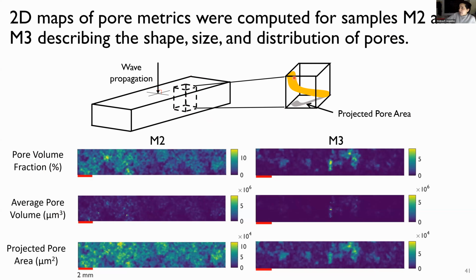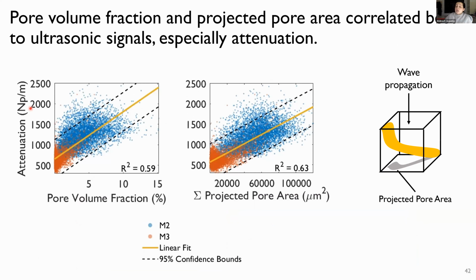So essentially, if we had a pore that was oriented like this, we wanted the area that would actually be perpendicular to that wave propagation direction, since we anticipated that that might have some good correlation to the ultrasonic parameters. Now, keep in mind, we considered a lot of other metrics that are not shown here. These were the three that showed us the most significant correlation to our ultrasonic results.